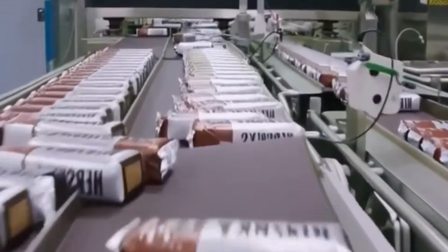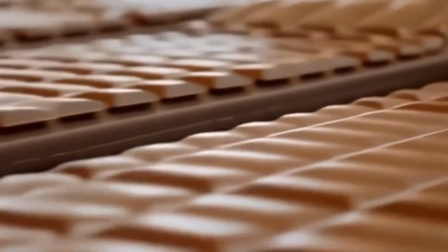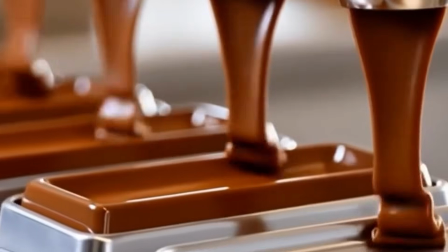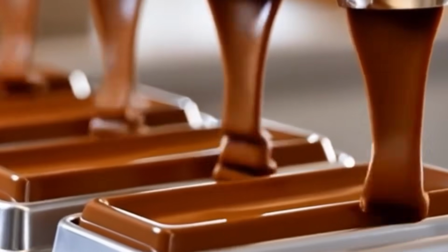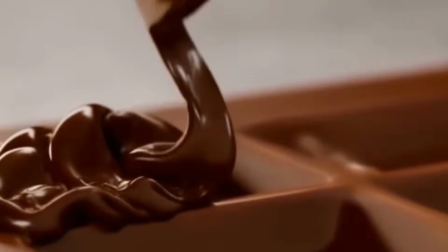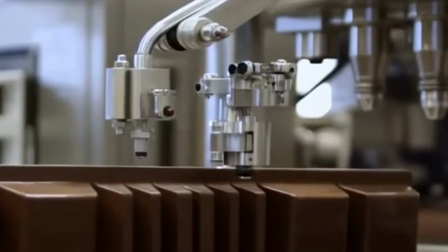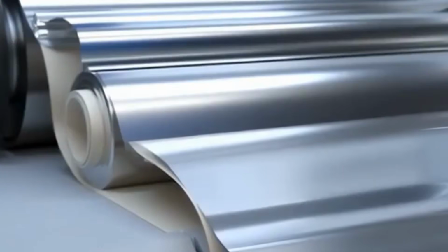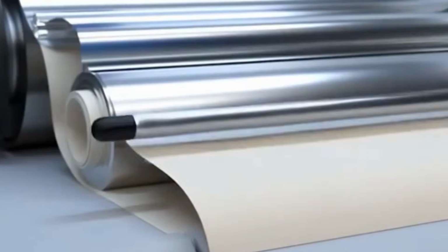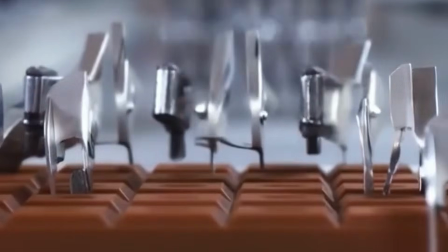When the chocolate has fully set, the molds are inverted and the bars are ejected using mechanical arms or flexing systems that pop the finished bars onto conveyor belts for inspection. Every bar passes under a series of vision systems that scan for surface defects, broken edges, misaligned logos, or irregular thickness, and any bar that fails inspection is automatically diverted for rework. Acceptable bars move forward to the wrapping section, where high-speed machines fold foil or film around each piece and seal it using heat or pressure depending on the packaging format.